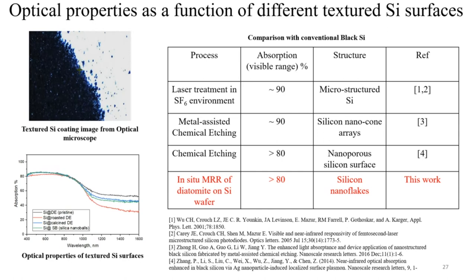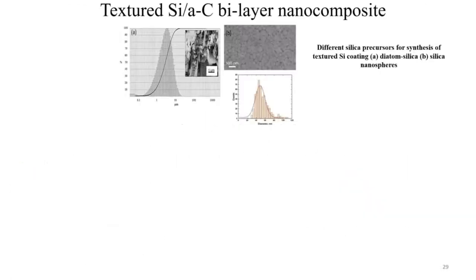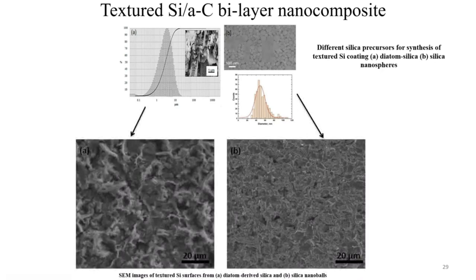substrates dramatically. The last part talks about textured silicon surfaces and amorphous carbon bilayer nanocomposite. As mentioned before, to evaluate the reproducibility of this technique, we reduced two different silica precursors, from diatomite, that's diatom silica, and also from silica nanospheres. And the two precursors led to nanostructured silicon surfaces, but with quite different morphologies, which could possibly be attributed to the fine powder from the nanosilica source.